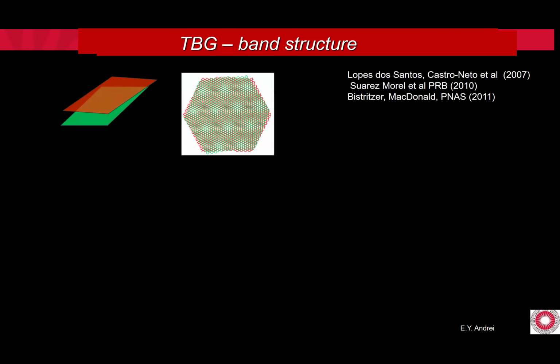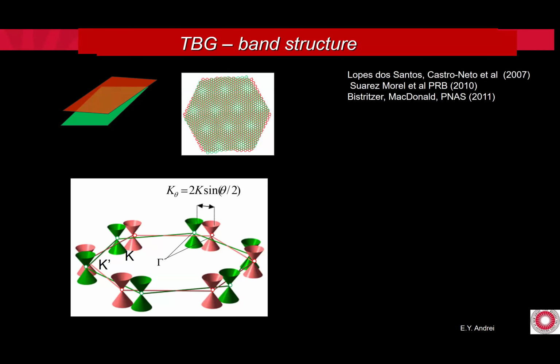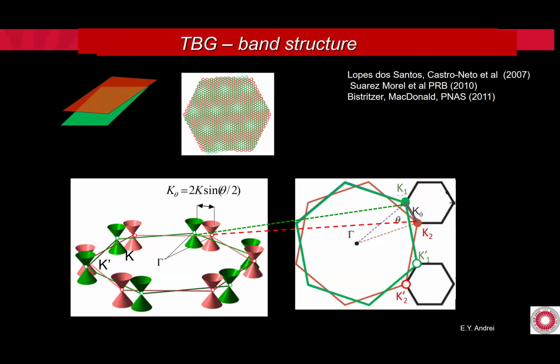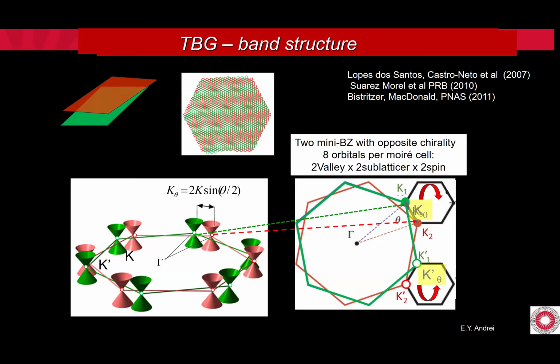So, okay, let's talk about the band structure. We have a top layer, bottom layer, Moire pattern. And in reciprocal space, they look like this: green for the bottom graphene, red for the top graphene. You see these two Dirac cones. Their separation is proportional to the twist angle in reciprocal space. We must remember that they have opposite chiralities because they come from the two K and K prime points that are related by time reversal symmetry. And we have 8 degrees of freedom, 8 orbitals per Moire cell: 2 valley, 2 sublattice, 2 spin.